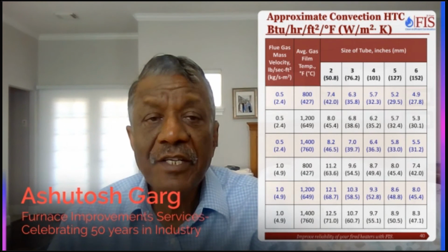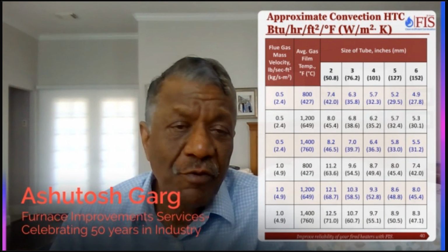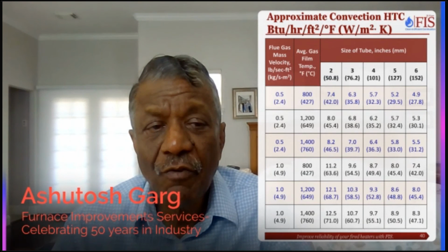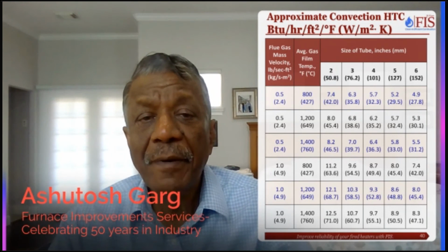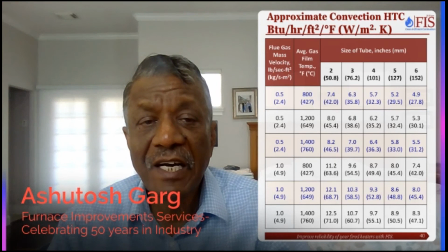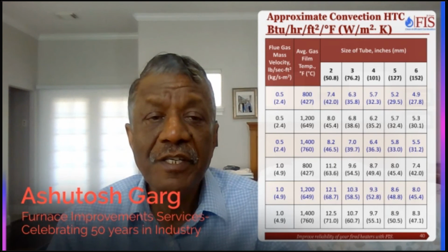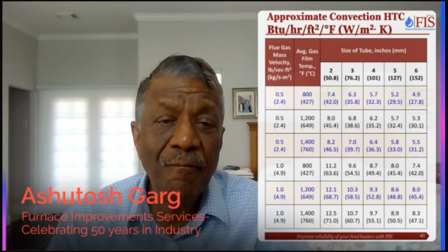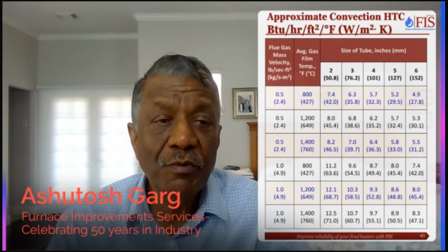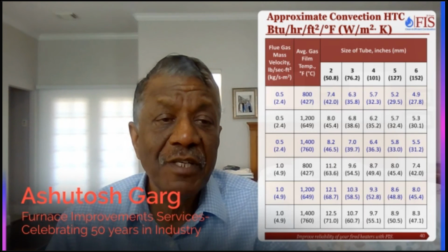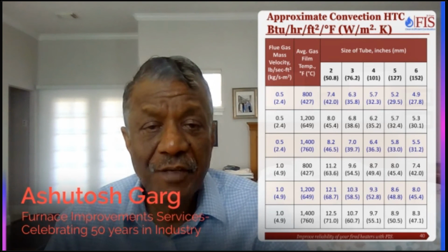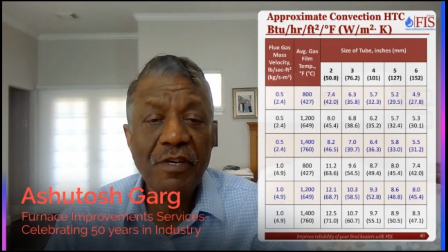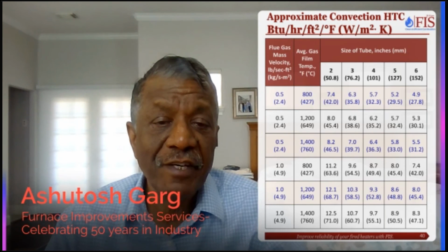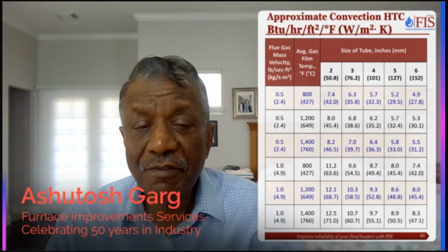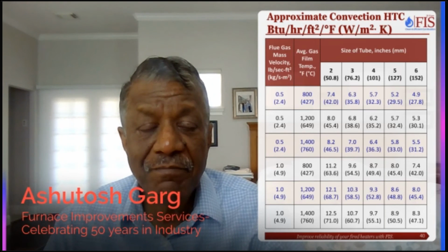So this is an approximate convection section coefficient. If you ever need to understand what type of coefficient should be there, depending on the flue gas mass velocity, depending on the average gas film temperature, these are the different tube sizes you can see over here. And as you can see, from 2 inch to 6 inch, for everything being the same, the heat transfer coefficient goes down. This is at 0.5 and this is for natural draft. This could be taken for induced draft. And you can see when we use higher flue gas mass velocity, the coefficient goes higher.